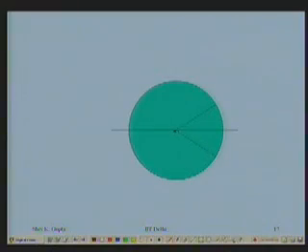Geometry of the diffraction. In the case of a camera, here is my specimen. This is the incident ray, that's the transmitted ray, and that's the diffracted ray. Between the diffracted ray and the transmitted ray, the angle is always 2 theta. That you see from the geometry of the Bragg law which I made. And the particular plane which is diffracting, let us say, is placed like this. So this angle is theta, that angle is also theta, but this angle becomes 2 theta. And this set of planes in another crystal rotated in this fashion gives rise to diffraction in this direction.